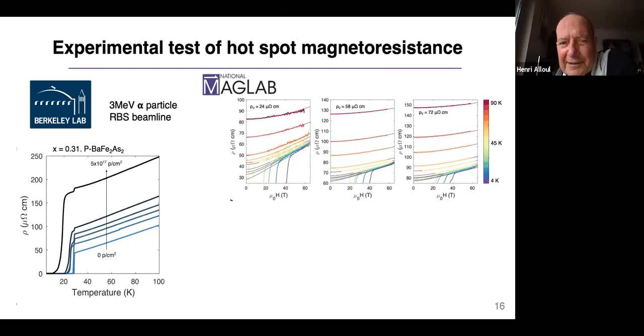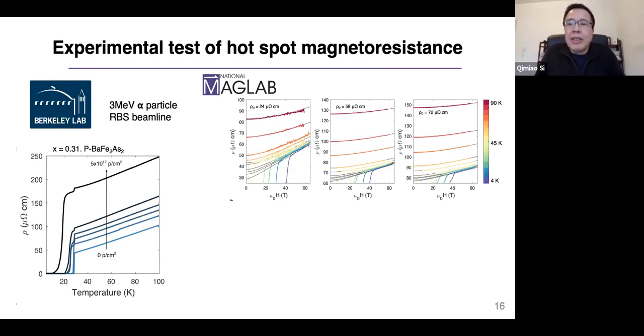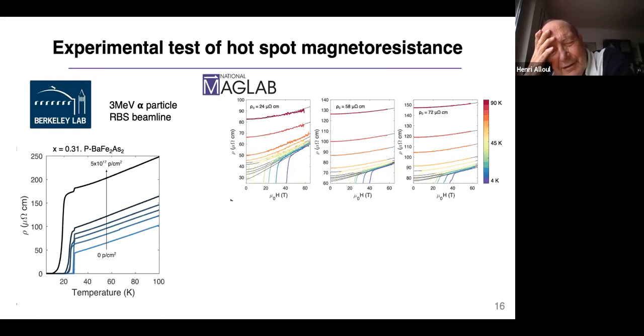I still have one remark. Can I go on? Yeah, go ahead, Henri. This system being multi-band, in principle, the scatterings are not going to be the same for the various bands. So the analysis that is done, which is similar to that done in the cuprates, is done for a single band model, where you think that the band has the hot spots. In any case, you also have other bands. So when you look at resistivity or magnetoresistance, you are seeing things which are adding the conductivities of the various bands. That makes it more difficult to analyze than the case of single band models like the cuprates.